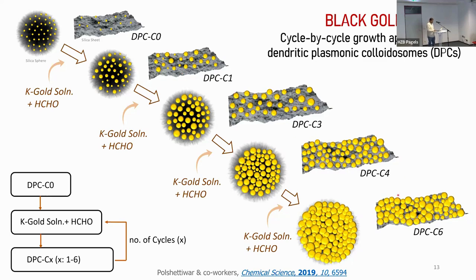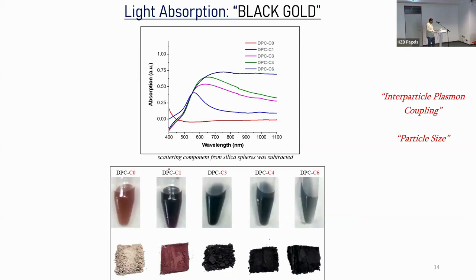And when we characterize them for the light absorption behavior, you can see a very weak light absorption when you put a 10 nanometer particle onto the DFNS. With decreasing gaps between the nanoparticles, C1, C3, you see a broadband light absorption. You achieve complete broadband light absorption from 400 nanometer up to 1100 nanometer. And that also changes the color of the gold.